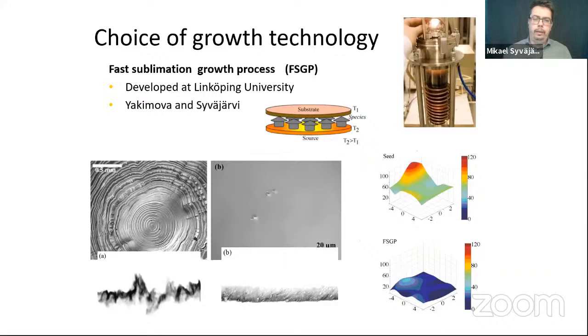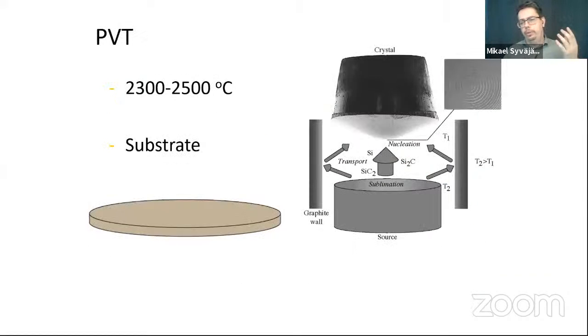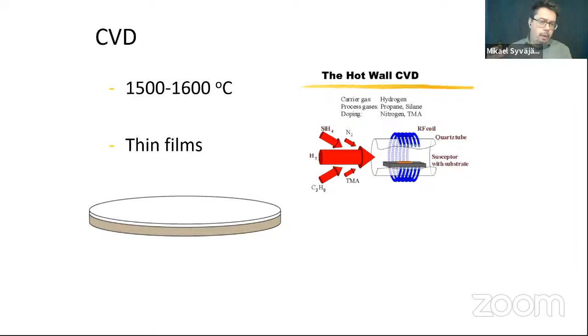And if we look into what we were doing, more or less a little bit unintentionally, we had the PVT growth method, but it's not useful for making thick films, and you have background doping and not good enough quality. And in silicon carbide, there is the more popular CVD system where you have gases containing silicon and carbon, but it's very difficult to have high growth rates and control this and do the doping, because it should be N-type and P-type doping. Nitrogen and aluminum are two that are controlled, but boron is much more difficult, and boron is always persistent in the reactors and so on, so it makes problems. So CVD was not the method which was most useful for the fluorescent silicon carbide.